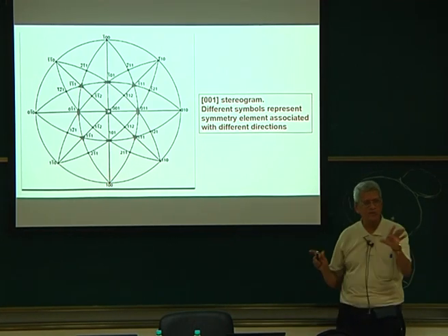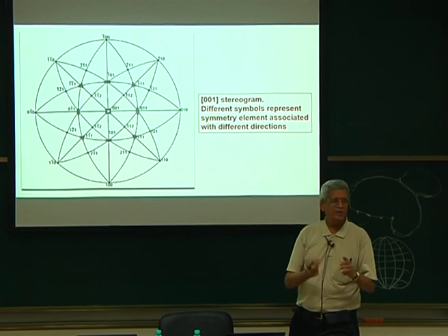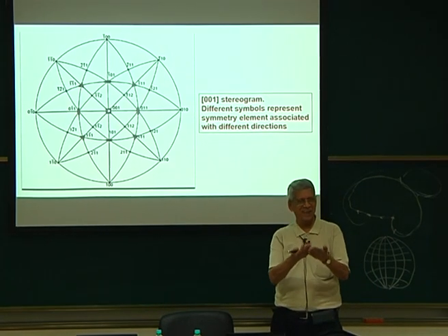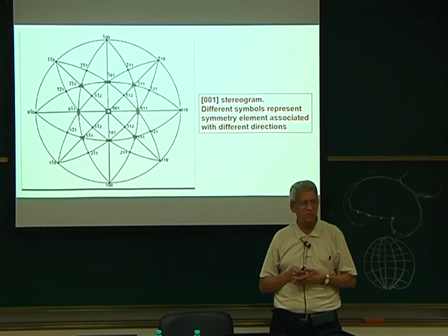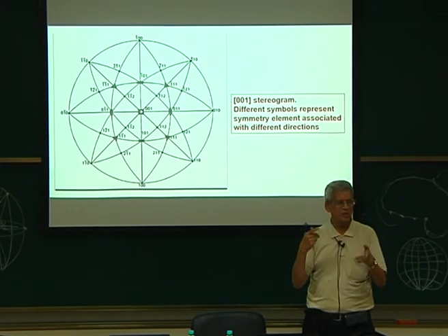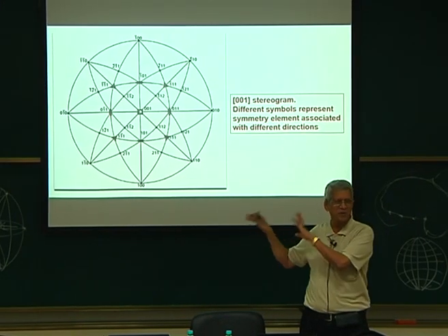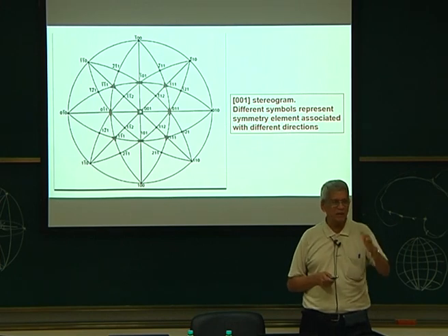Each of these angles, once it has been measured, you take the sine of it and take the ratio, and that ratio you make into an integer, that integer corresponding to the index of that plane. That you can find out, yeah.